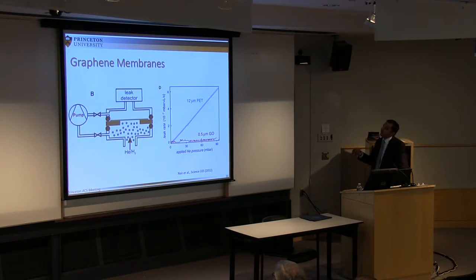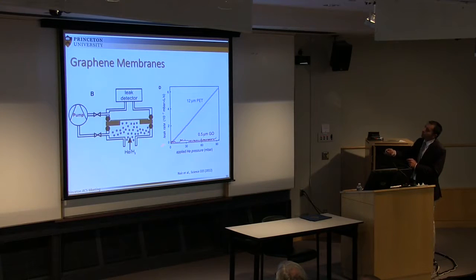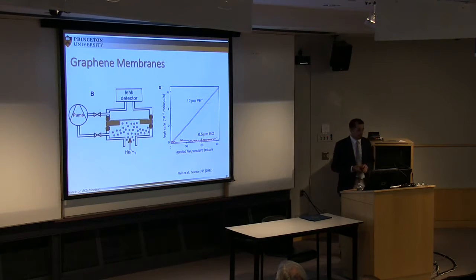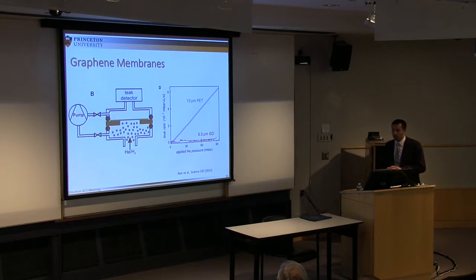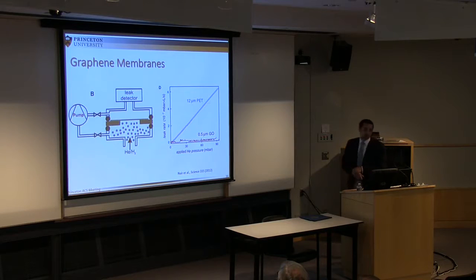And similarly, they did the test with gases like helium, H2, N2, and what happens there is that when you have the non-reduced graphene oxide membrane, you have no leak, so nothing goes through, or very little. But if you use a conventional polyethylene terephthalate membrane, the gases can easily go through.